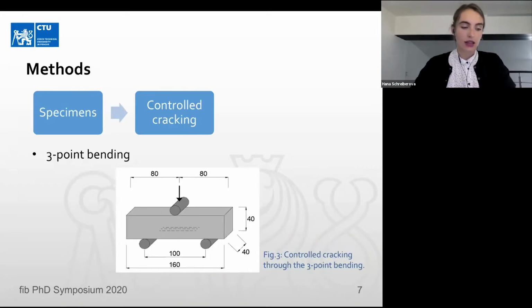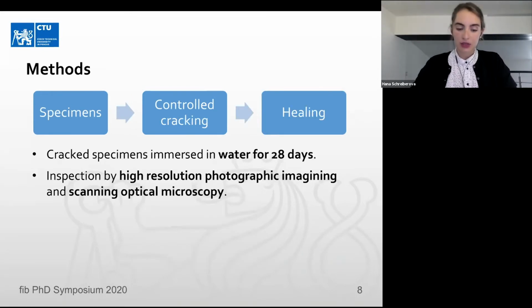Then, at the end of the curing period, the samples were subjected to controlled cracking. So the reinforced beams were slowly loaded through a 3-point bending test, so a crack would form in the middle of the span of the specimens without complete loss of the sample's integrity, as you can see in figure 3. Then the cracked samples were placed into water-filled plastic containers and left at room temperature for 28 days to heal. Before and after the healing period, the cracks were monitored through high-resolution photographic imaging and scanning optical microscopy.